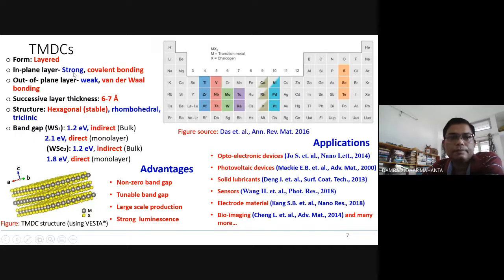Now here I will take not all examples, a few examples on which we have worked a little, whatever we can. The WS2 material has a band gap of 1.2 electron volt, which is an indirect type band gap in bulk form. But when it comes to monolayer form, it becomes direct, and band gap enhancement is also found, about 2.1 electron volt. For WSe2, it is 1.2 electron volt, and it can come up to 1.8 electron volt in the monolayer form.